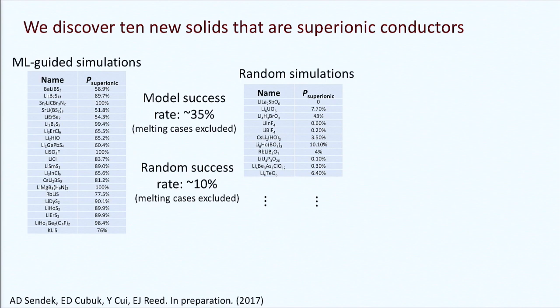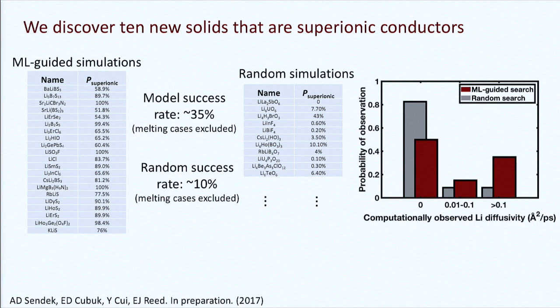This histogram shows how much better the results are when you listen to what machine learning tells you. The far-right column represents really good conductors; the far-left represents really bad conductors. The red bars show what you find with the machine learning-based approach versus the gray bars — things discovered at random. Learning from only 40 data points — which from the perspective of folks at Google or Facebook is essentially zero data points statistically — drives a 3x improvement in the number of discoveries. We also have one very new exciting material discovered through this process that we can't yet share as it's not published.